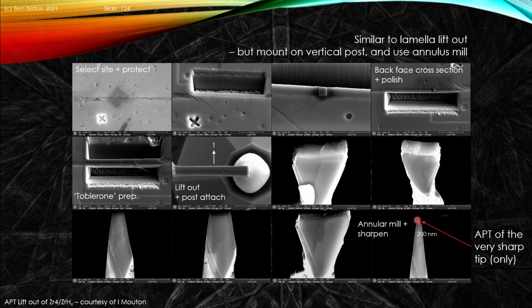And we'd like a reasonable aspect ratio so we can get a fair amount of distance evaporated. If the needle is too sharp though, you can get some issues where the atom probe needle may crack when it's being evaporated using, say, voltage pulsing or laser-based methods.